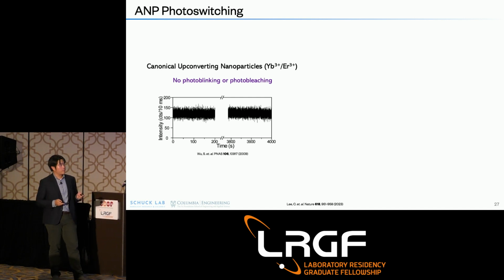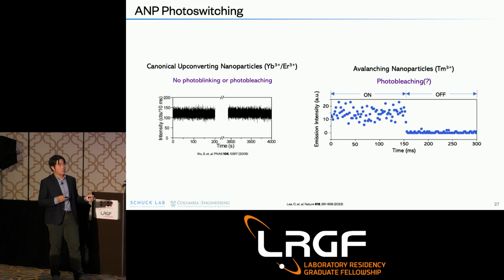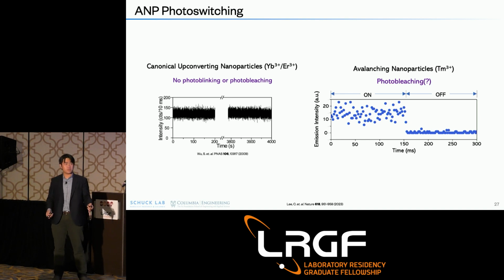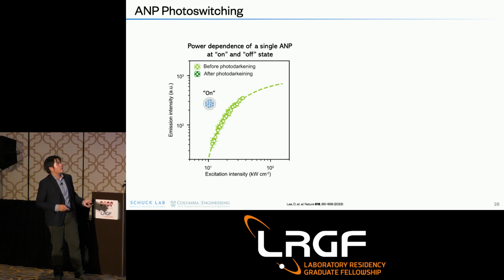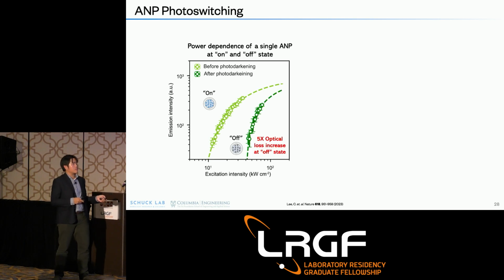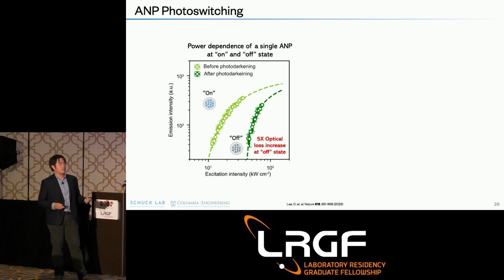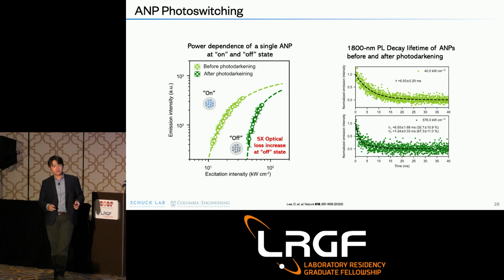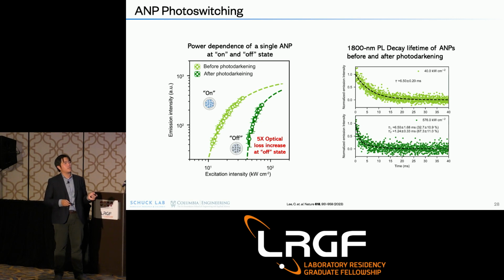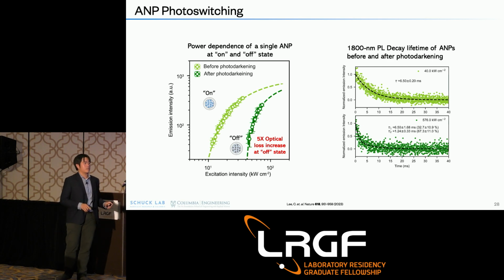But in ANPs, the avalanching nanoparticles, what we see is that after some amount of laser radiation, after some amount of time, the particle starts to just turn off, which is unusual for this sort of material. When you look at the S curve of this material in the on state compared to the off state, you can see that the S curve varies drastically, and the off state has more or less 5 times the optical losses. And when you look at the ground state transition, in particular using fluorescence lifetime measurements, you can see that the lifetimes are also very different, meaning that there's some interesting physics happening at the nanoscale.